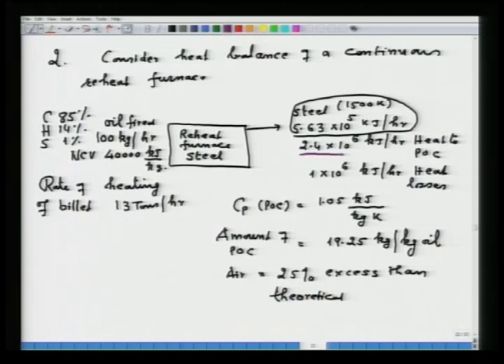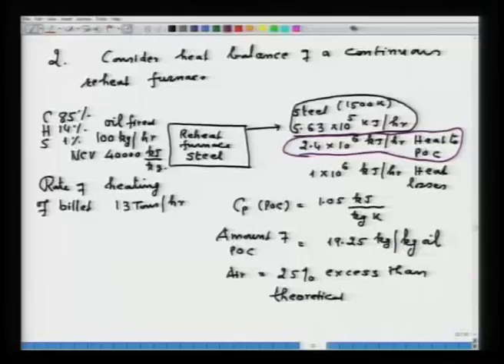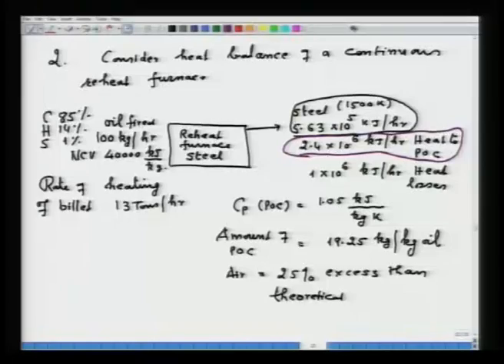Now, if you think in terms of bringing down the fuel consumption of 100 kg per hour to a lower value, the only alternative that seems to be applicable in this particular scenario is what can be done with the heat to POC. What I mean, if you are working in a plant or in a rolling mill where steel is heated to that temperature and they are not using that particular heat, heat balance is before you. So, you should think about what can be done to bring down the fuel consumption in the existing furnace. Mind you, I am talking of an existing furnace, and by this heat balance it comes to your knowledge that 2.4 into 10 to the power 6 kilojoule per hour of heat is being taken by the POC.